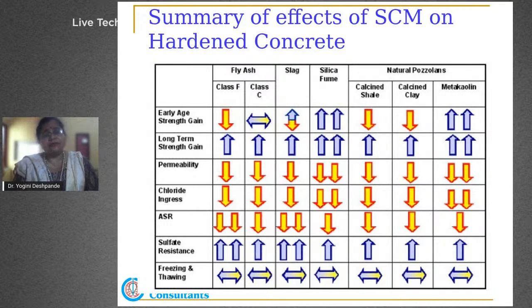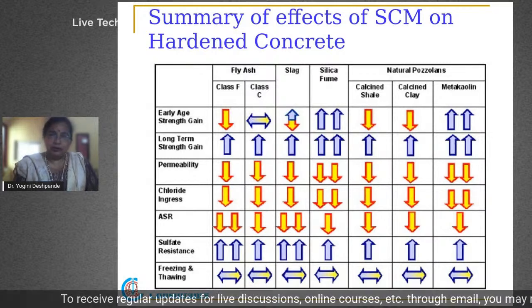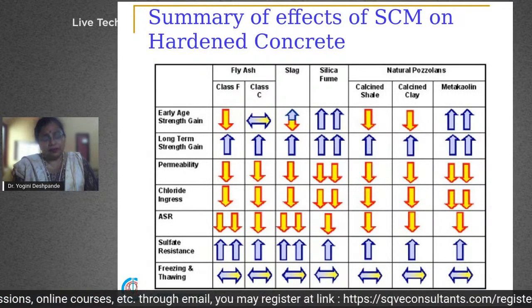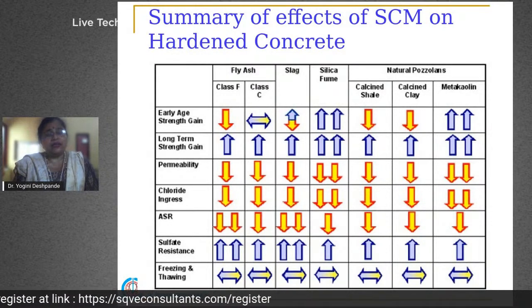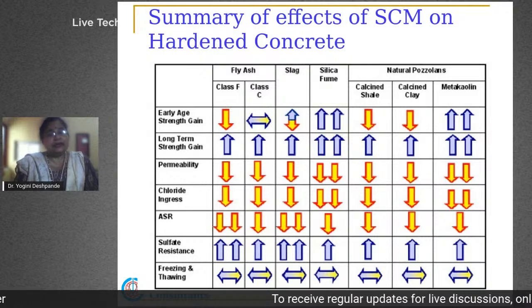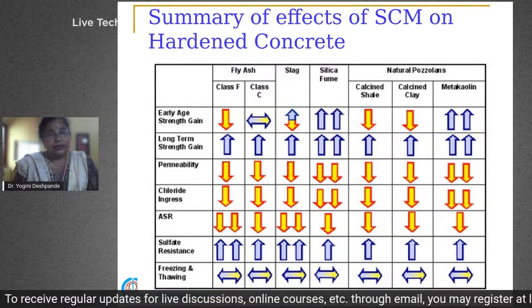Chloride ingress, as I mentioned, also gets reduced in the same way. Alkali silica reaction, or alkali silica reactivity, we don't come across much in India except in regions of Orissa, Chhattisgarh, Jharkhand to a certain extent, and some states in the northeast like Tripura and Mizoram, where slightly unstable compounds or elements may be found in the aggregates. But typically, alkali silica reactivity, which happens about 5 to 7 years after concreting, will get reduced when we use fly ash or slag together.